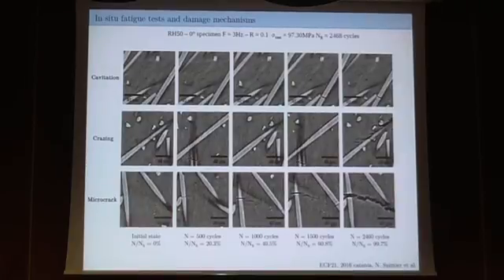Cavitation. We did some experiments in uniaxial test. I don't show you these results, I have no time, but cavitation was really pronounced in fatigue testing. We did not observe it in quasi-static testing. It's a really particular mechanism of damage that appears for fatigue loading.